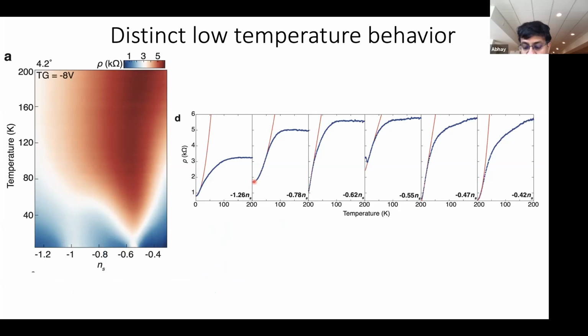If you go to a special point, which is exactly at this metal insulator transition as a function of doping, we find that the resistance is linear in temperature all the way down to the lowest temperature. The lowest temperatures we've measured are down to 0.2 Kelvin, and it's linear all the way down to that temperature. Then exactly at 1/2 filling, at the lowest temperature, you see insulating behavior. So that's the insulating behavior that shows up.